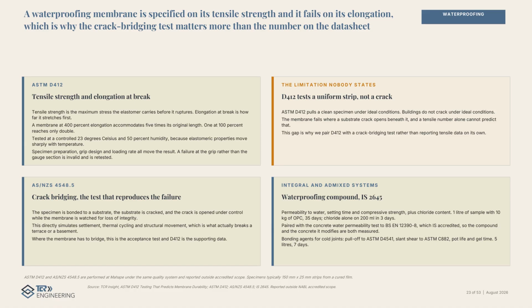But ASTM D412 pulls a clean strip under ideal conditions, and buildings do not crack under ideal conditions. So we pair it with the crack bridging test under AS-NZS 4548.5, where the membrane is bonded to a cracked substrate and the crack is opened while the membrane is watched.